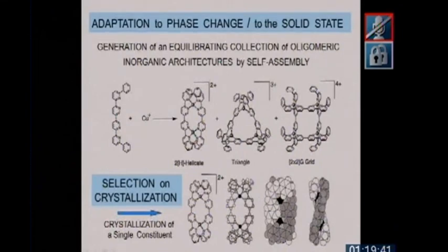But since all of those are in equilibrium, when the helicate crystallizes, these transform into helicate, so that at the end of the crystallization, there's nothing left in solution. It's not like a normal crystallization, where what crystallizes is one compound, and all the others remain in solution. Here, what crystallizes is one compound, but all the ones in solution transform into this one. In other words, the forces of the solid network have driven the system to generate only one entity because the solid packing has selected this structure.